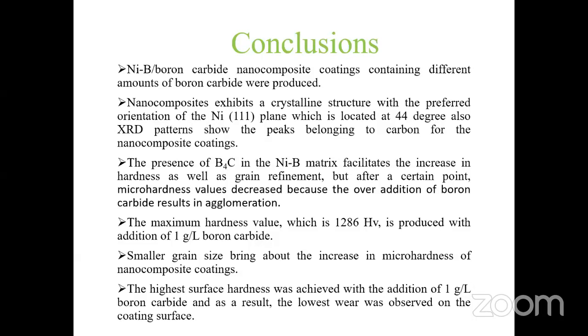Smaller grain size brings about the increasing microhardness of nanocomposite coatings. The higher surface hardness was achieved with the addition of 1 gram per liter boron carbide, and as a result, the lowest wear was observed on the coating surface.